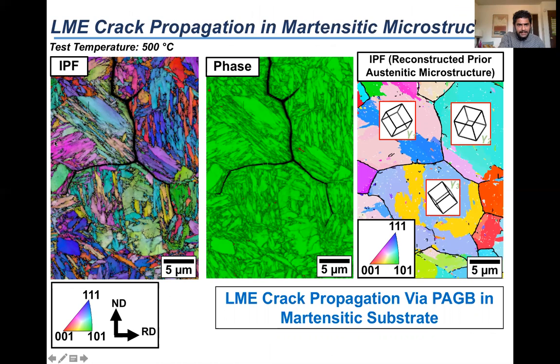So we use the EBSD IPF to reconstruct the prior austenitic microstructure, the austenite that was present before the martensitic microstructure was formed. So here is the EBSD IPF of the reconstructed prior austenitic microstructure, and what do we see? So here is the LME crack over here corresponding to this, and what we find is that the prior austenite orientations on the two sides of the crack are different, which means that the LME crack in the martensitic microstructure was formed via prior austenite boundaries, not lath boundaries, not block boundaries, not packet boundaries, nothing. Prior austenite boundaries were responsible for forming LME cracks.